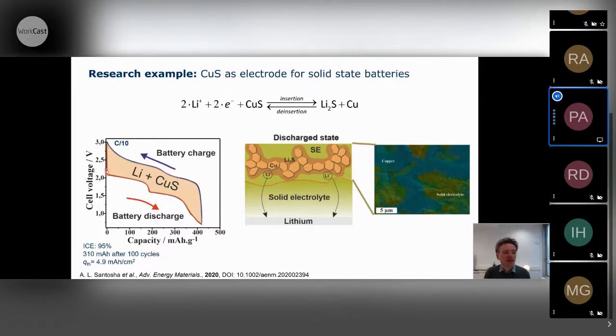And you can see this is a charge and discharge curve at C/10. This is the conversion reaction of lithium with copper sulfide, and you can see it is also a highly reversible process. The very special aspect of this reaction is that the end product here is copper. For conversion reactions, usually you form nanoscopic particles. In this case, you form really macroscopic particles and crystallites. And this is shown here.